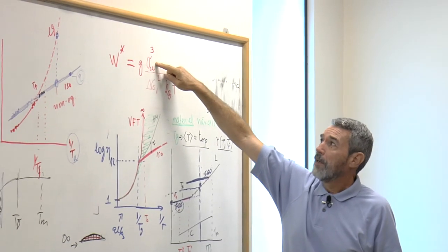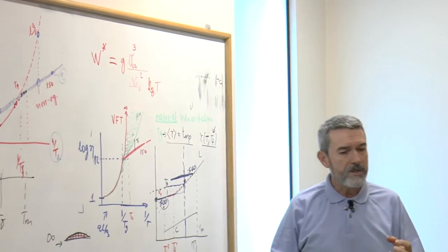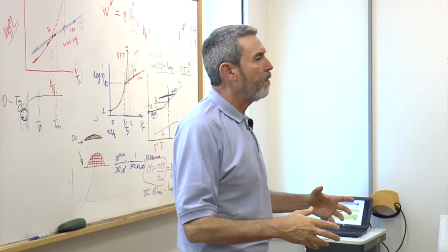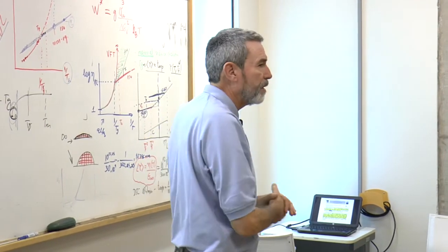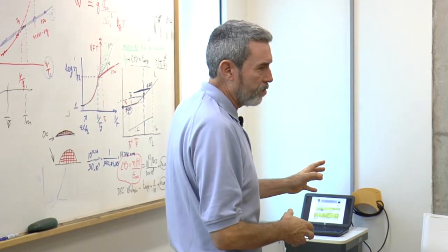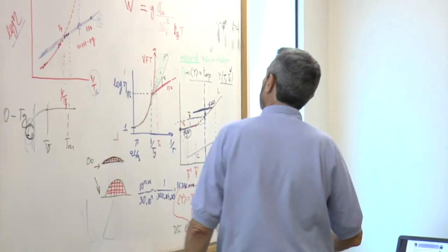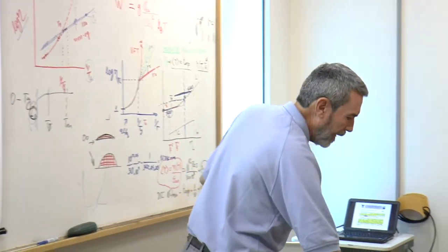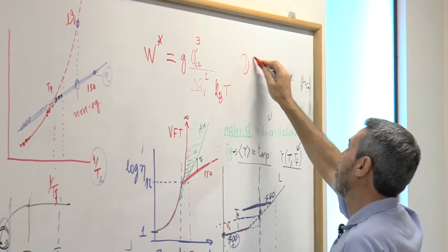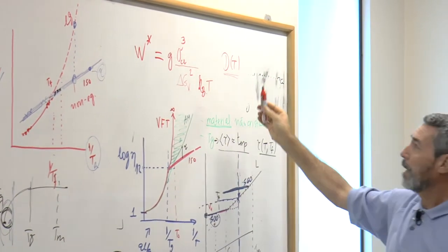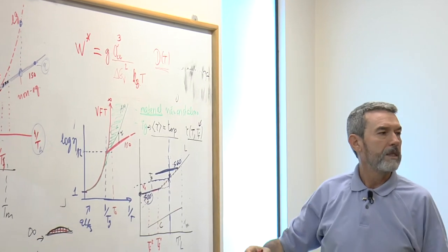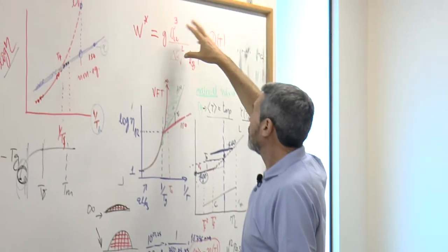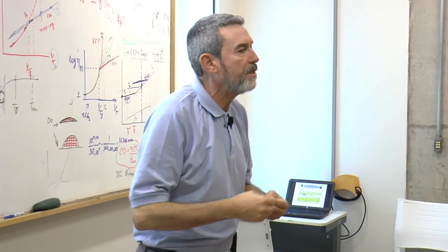If the surface free energy between the crystal and the liquid is very high, it'll be almost impossible to form a nucleus. If it's very low, it'll be easy to form a nucleus. So it's a balance between all these parameters. This is a thermodynamic barrier. And then there is a kinetic barrier also. As in the relaxation, there is no barrier; it's just kinetic diffusion, just a diffusion barrier. For nucleation, you have a thermodynamic part and a diffusion part. I'm going to talk about this in three or four more classes, diffusion and thermodynamics. Relaxation is only diffusion. It does not need to overcome any barrier. It's spontaneous, it starts immediately.